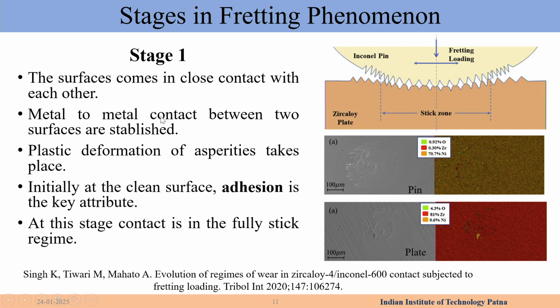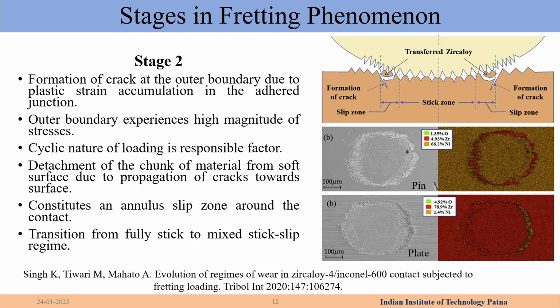In the first stage, the surfaces are in close contact, metal to metal between 2 surfaces, established, with plastic deformation of asperities. Adhesion is happening at this stage. Okay. So this study was an attempt to draw a wear map in time, to understand with time whether these stick and slip zones change and how they change over time.